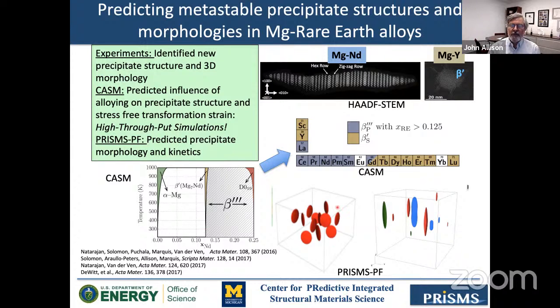Then we did use those stress-free transformation strains and interfacial energies to drive in the free energies from the phase diagram to drive prisms PF. And in the Mg-neodymium alloys, we saw these lenticular precipitates form. We predicted them to form. And in these Mg-yttrium type alloys, the beta prime S, which are rod type like precipitates.